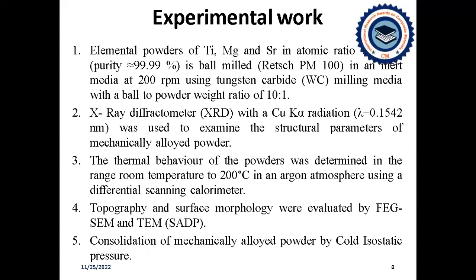Experimental work. Mechanical alloying is one of the most important techniques. We know the effective way to improve the atomic interdiffusion, through a continuous cycle of flattening, cold welding, and fracturing of powder particles, is possible only by the route of mechanical alloying. Hence, the elemental powders of titanium, magnesium, and strontium in the atomic ratio 70 to 10 to 20 are ball milled in an inert gas atmosphere at 200 rpm using tungsten carbide as the milling media in the ball to powder weight ratio of 10 to 1.